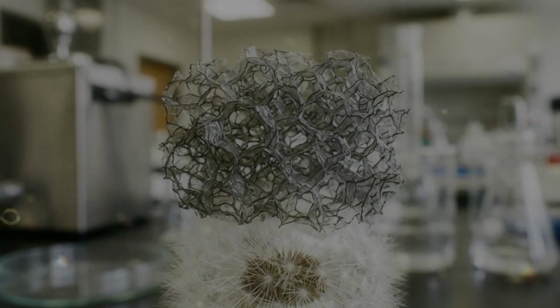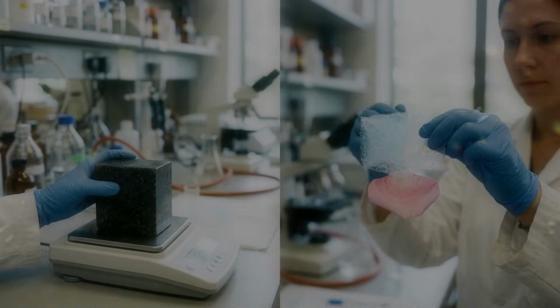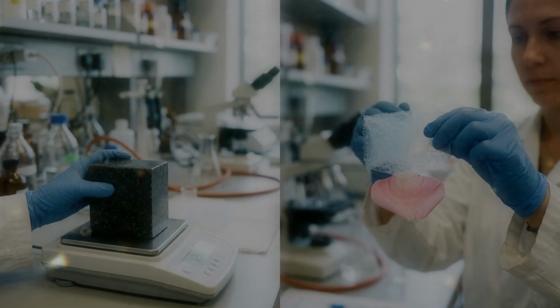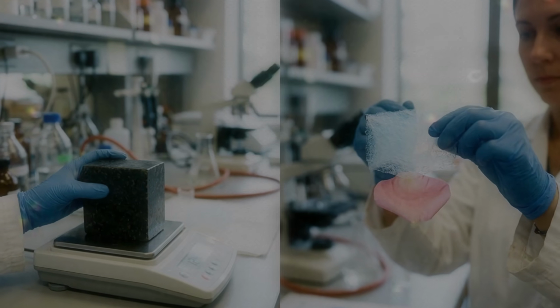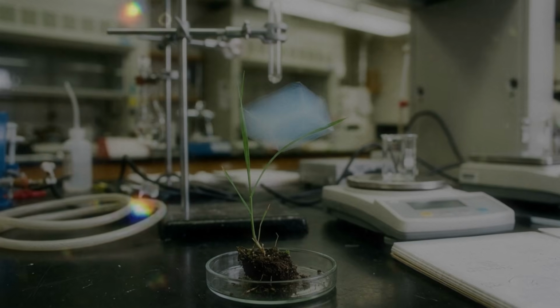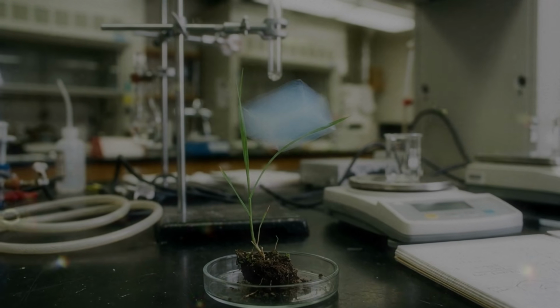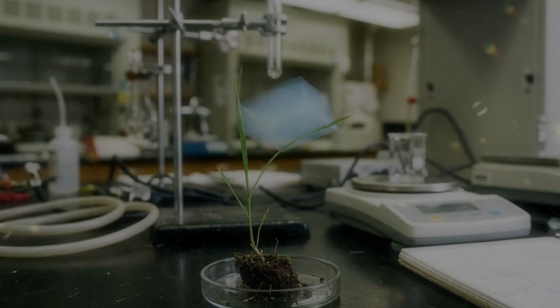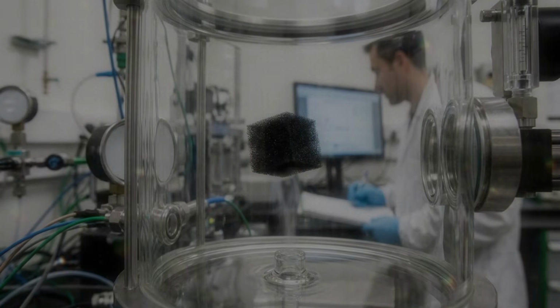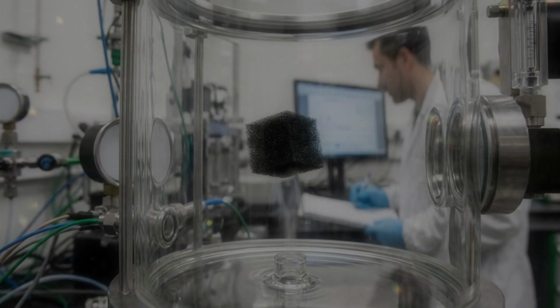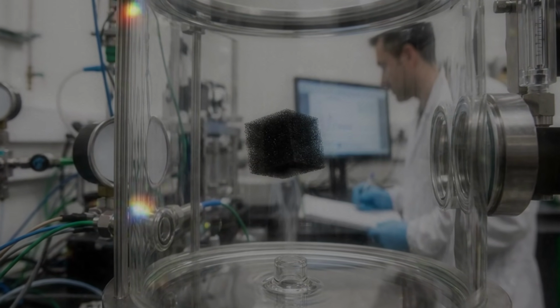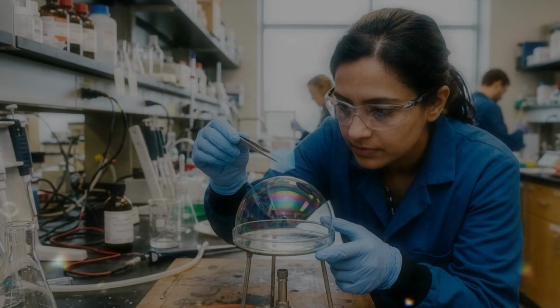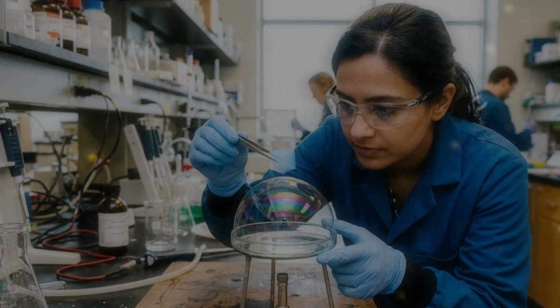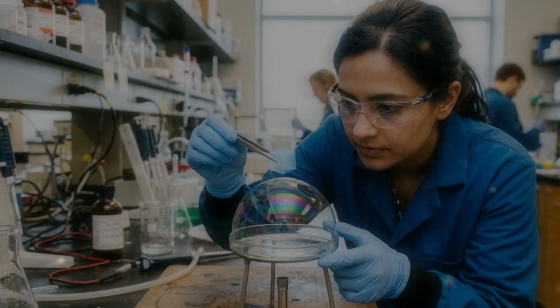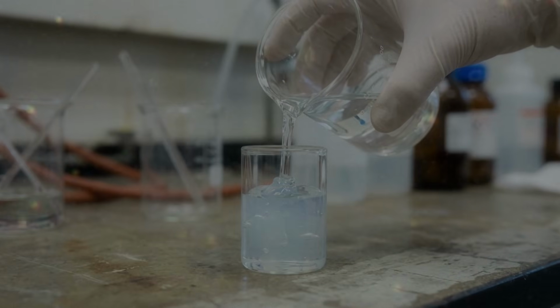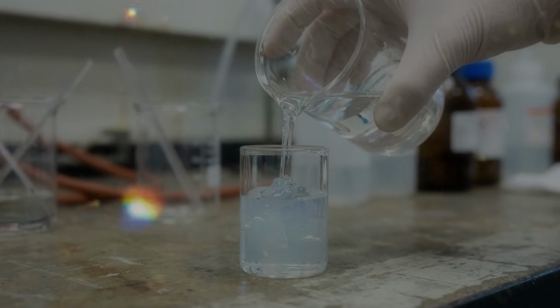The internal surface offers many places where charge can gather or chemical reactions can occur. Very small pores increase the available area, but they can slow the movement of charged particles. Larger channels allow faster transport but provide less surface. A successful electrode often needs both. Large pores act as entrances. Medium-sized passages distribute the liquid. Small pores provide active surface. The different scales work together, much like main roads, local streets, and paths leading to individual houses.